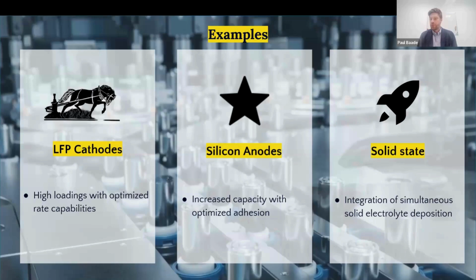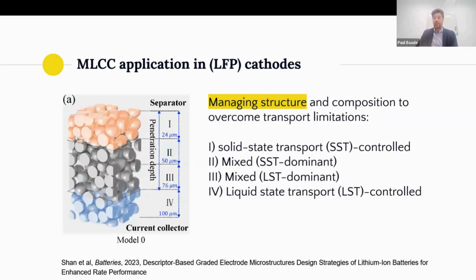And I wanted to share examples of what we do and how we create value for these different applications, to mainly showcase the versatility of our coating technology and what kind of value mechanisms we can bring. So if you look at cathodes, I think the problem with LFP cathodes is particularly prominent. LFP having a rather low volumetric energy density, LFP electrodes are usually quite thick. If you look at loadings at 3 milliamp hours per square centimeter, or even 4, 5 and 6 milliamp hours per square centimeter, you're talking about electrode thicknesses way thicker than 100 microns, 150 even. And that means ultimately you run into transport limitations.